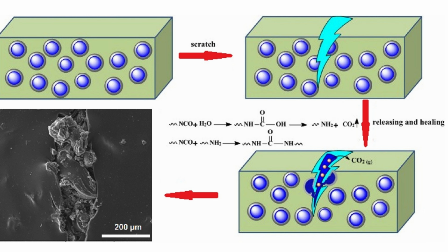Furthermore, following the occurrence of microcapsule rupture and polymerization, the microcapsule is rendered incapable of initiating the healing reaction. This phenomenon causes a limited number of healing times for the material and the inability to satisfy multiple healings in the same place. Hollow fiber-based self-healing materials.